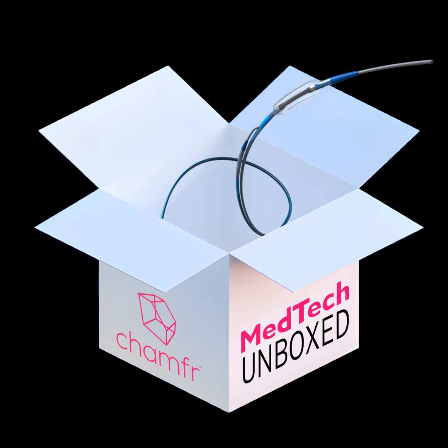Up on the screen here, I have shared the dimensional requirements that we try to maintain: the ID within 1.7% of the nominal ID, the wall thickness within 5% tolerance, and the concentricity greater than 90%. The ID is really critical to our ability to expand the extrusion to the balloon diameter. This is where the mechanical properties of the tube are so important, because we can only stretch the tube so much, so maintaining the ID is really critical.